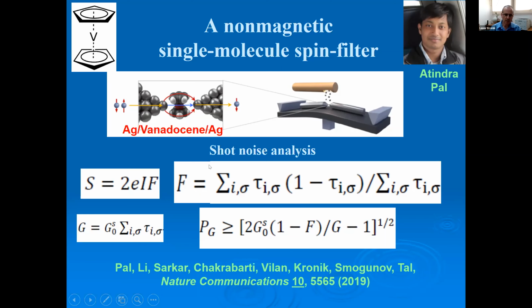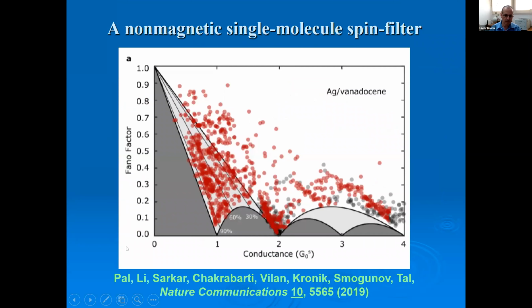So one can use that to create a plot that looks like this, where we take all kinds of possible transmissions. For each, we calculate the Fano factor and the conductance, and we make a plot. So the dark gray areas in the plot mean that it never happens. There is not a single point of data that falls in there, even theoretically. The gray areas mean that it's possible, but it will be spin polarized to varying degrees. And the white area means that it's possible and there is no spin polarization.